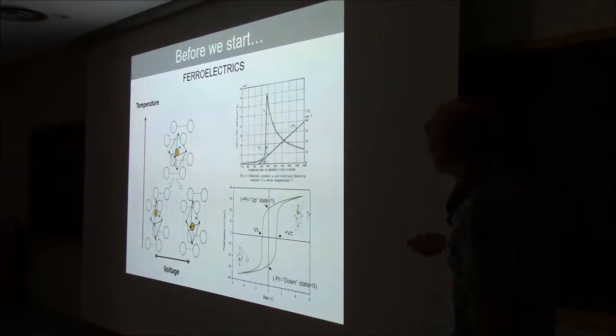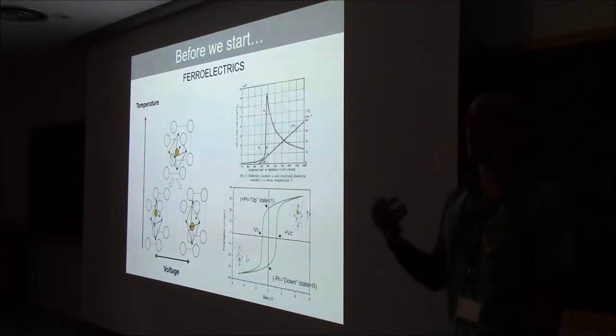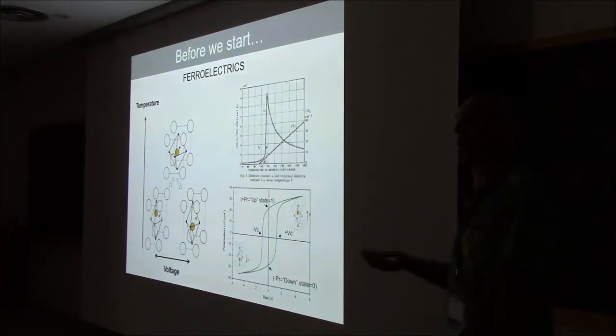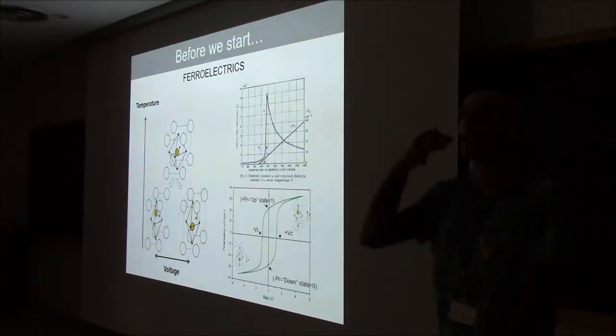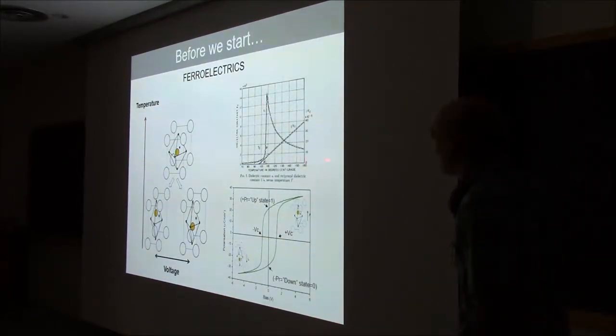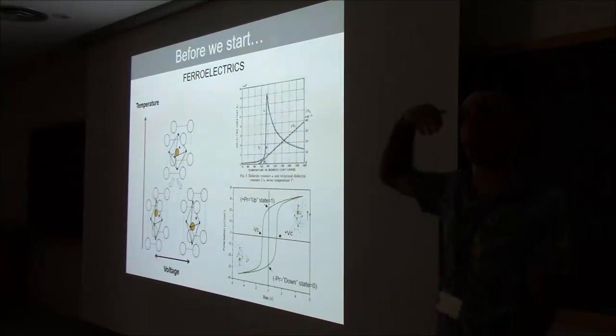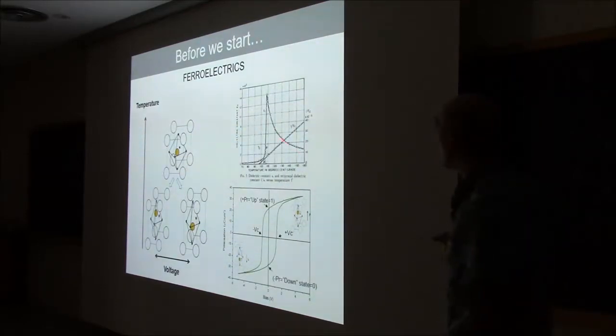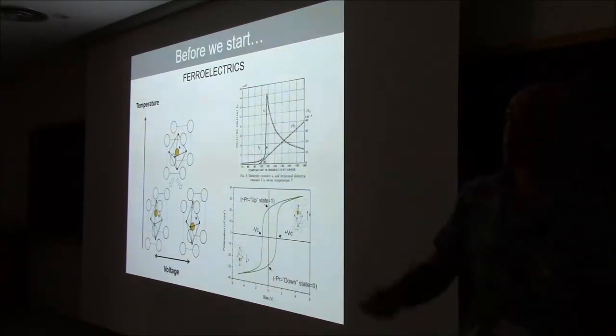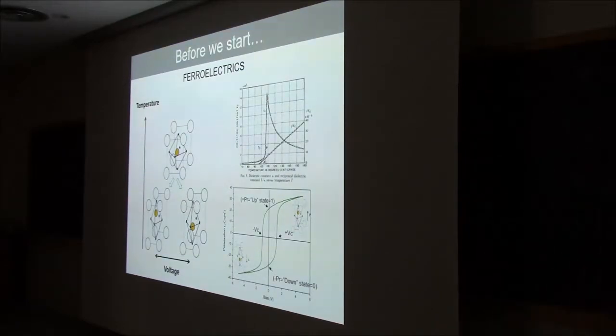In between the high temperature paraelectric phase and the low temperature ferroelectric phase, the material doesn't quite know what it wants to be, which means that it's extremely susceptible, and so its dielectric susceptibility goes through the roof. You have a very highly polarizable unit cell, and you have a very high dielectric constant, which is also very useful.